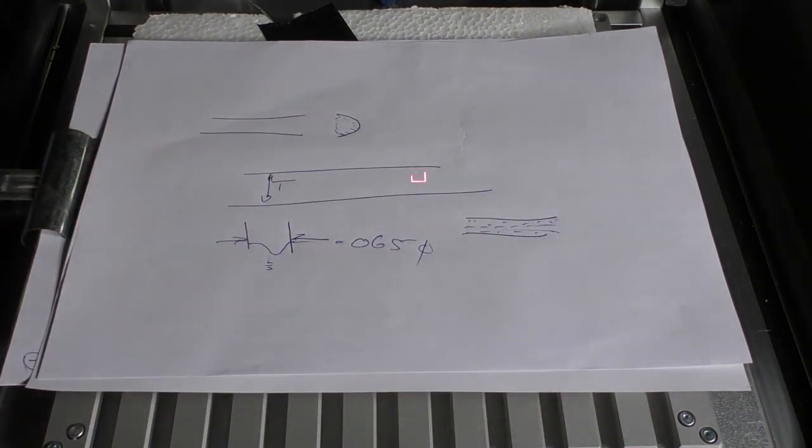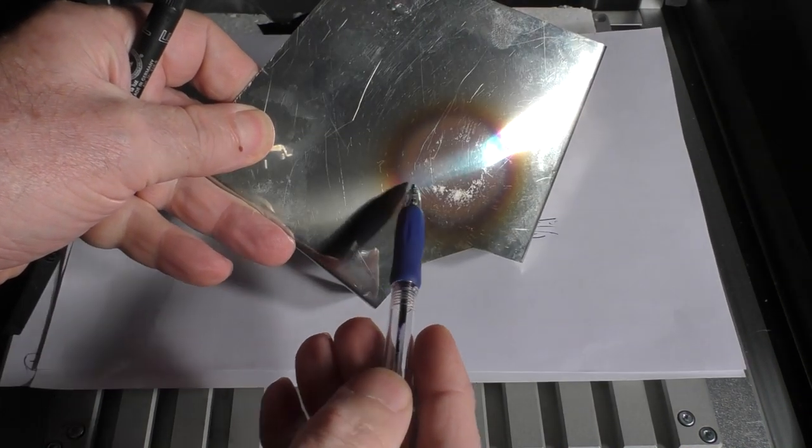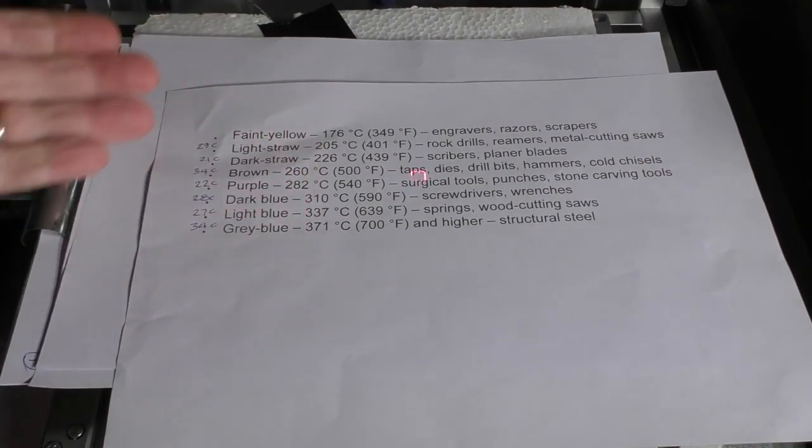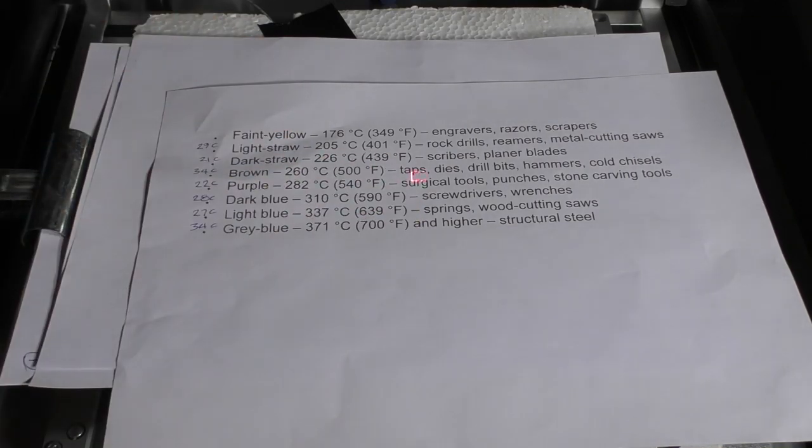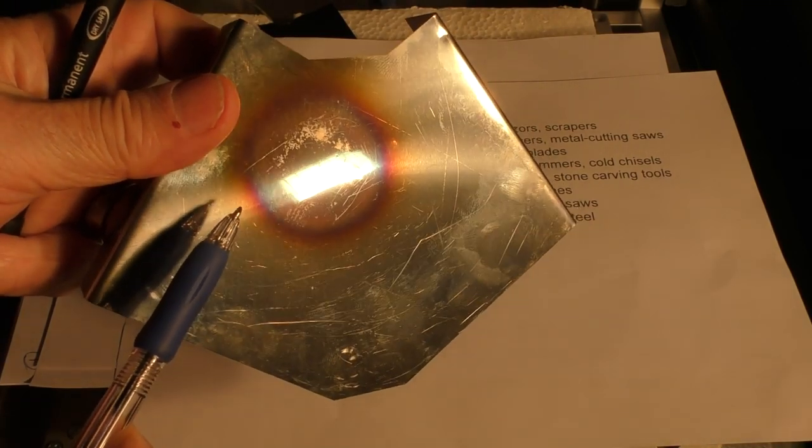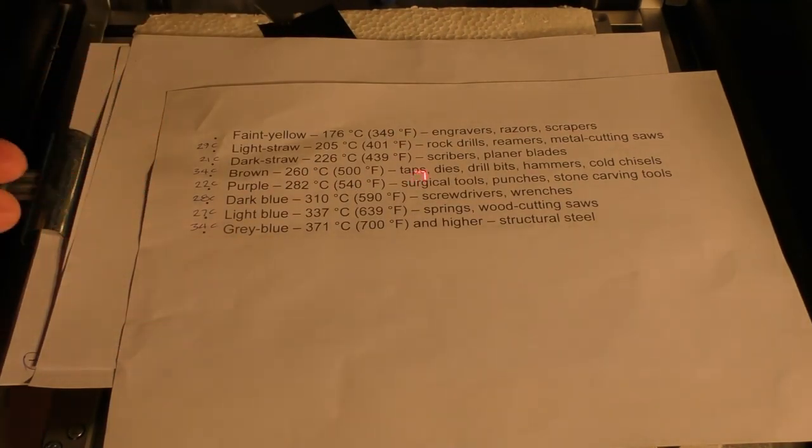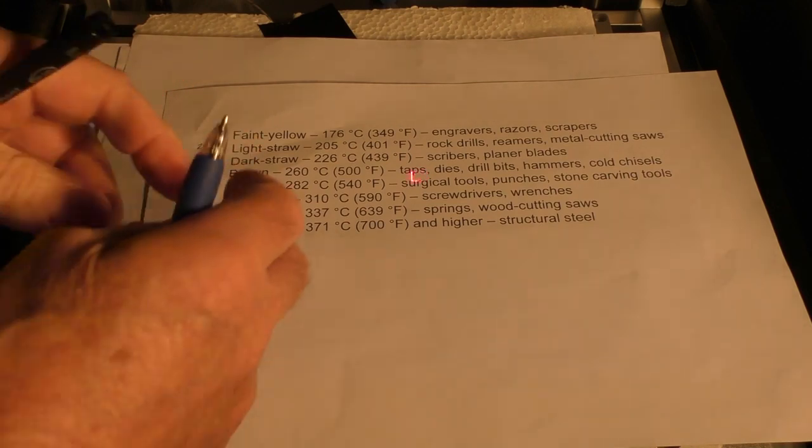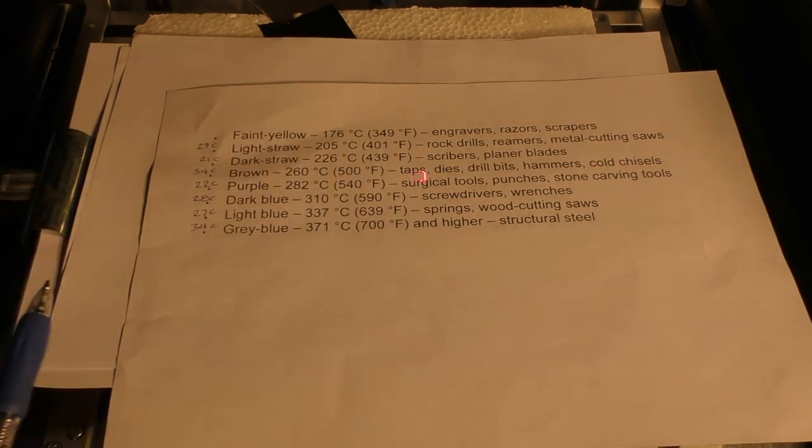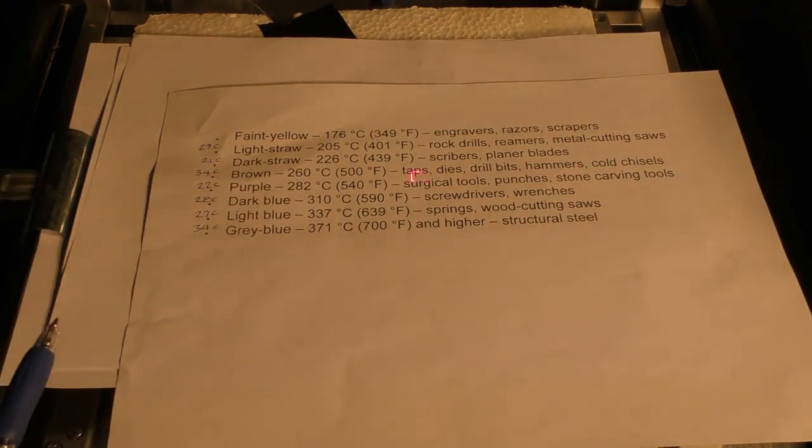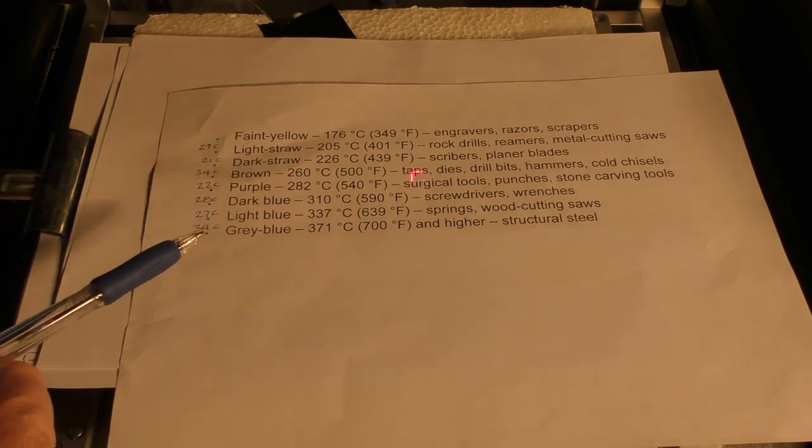So observation tells me that we've got lots and lots of strategies to play with here. Now as we found out from here, there are rules that govern these colors and those rules are these very simple temperatures. So what we've got to do is find a way of somehow inducing these sorts of temperatures into the surface. Now if we're melting, that's a bit interesting because you remember that when we heated this surface up in the middle here to red hot, it cooled down to blue. So I don't know how melting is going to give us this yellow color. I suspect we've got a very large thermal gradient away from where the actual beam is to the very small area around it. So I've got this problem of trying to work out how to keep the heat energy into a specific area.